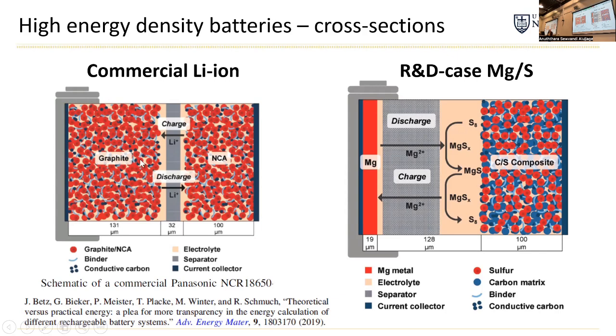And so every battery is composed of the two electrodes, right, which are separated by the electrolyte. And what they highlight in this schematic is that in commercial lithium-ion cells, both of these electrodes are very dense composites, right? And so they're highly filled particulate systems where the active materials are in the form of particles, and they are held together by a small amount of polymer binder and mixed with a carbon additive, and they form this very thick tortuous layer.